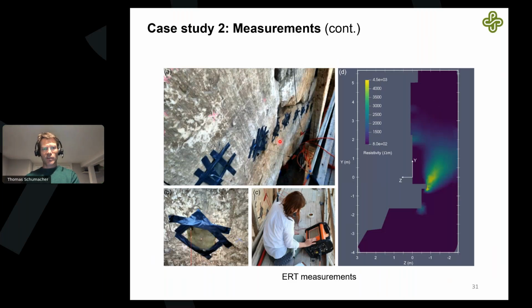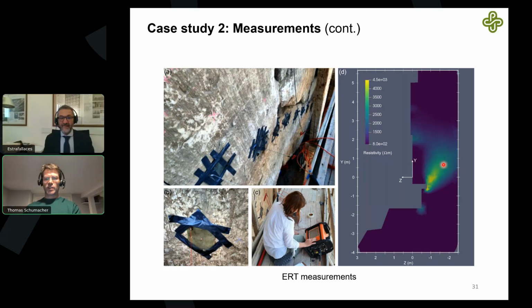Electrical resistivity tomography: these are the electrodes glued on or attached. You inject the current and measure resistivities at the other electrodes. You can then reconstruct the resistivity map. This is actually a vertical cross section. This is the chevron blocks here. You can see there's a high resistivity volume behind the blocks, and that's one of the things we couldn't tell with radar or GPR.